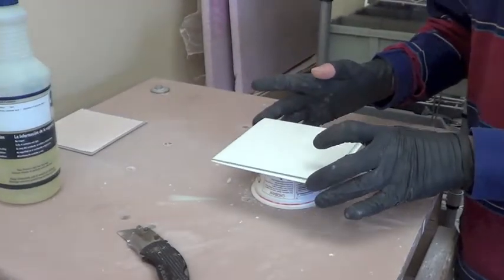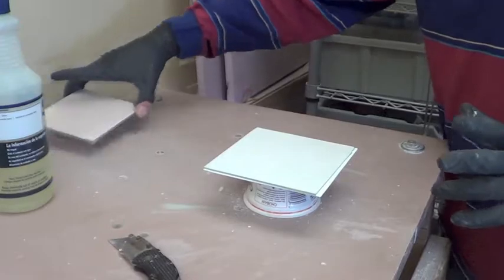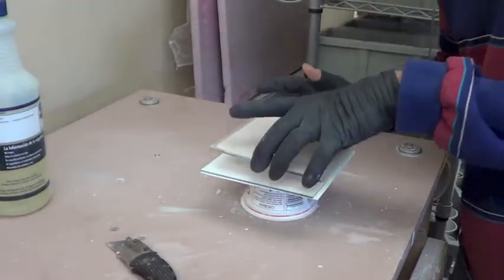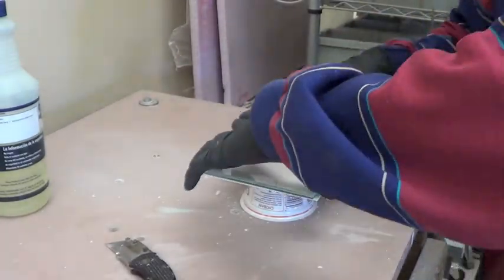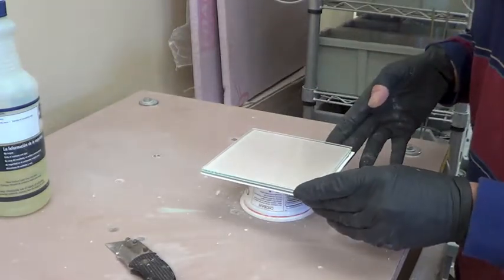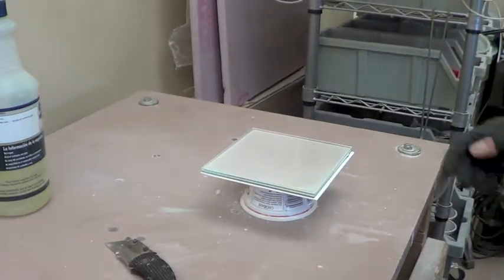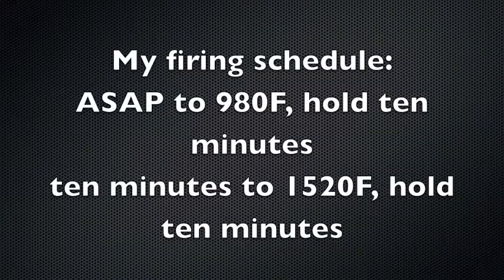Now make your sandwich. It's important to use the glass with the hardened mixture on it as the top side of the tile. I put both pieces onto a 5x5 piece of aluminous substrate. I'll make another video about aluminous substrates. And here's my firing schedule. I go as quickly as possible to 980 Fahrenheit, hold for 10 minutes, then 10 minutes to 1520, and hold for 10 minutes, then cool.